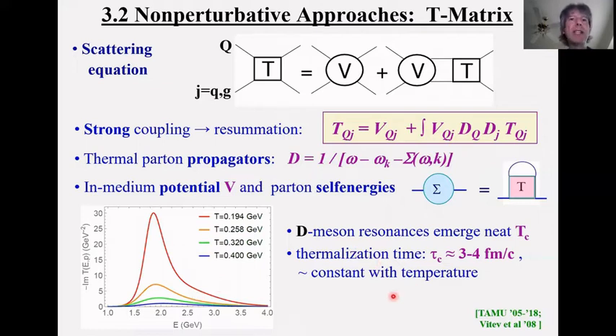That should not be surprising because as you go to lower and lower temperature, the potential should approach that of the vacuum. And if it's a realistic potential, then it should produce the vacuum D-meson mass. And indeed, this peak here is close to that vacuum D-meson mass. Also in this approach, you get rather small thermalization times, down to maybe 3 to 4 fm/c. And you also find that this thermalization time does not really decrease with temperature because you're losing interaction strength. These resonances dissolve, and that is compensated by the increase in the density of the medium, so that at the end of the day, the thermalization time is more or less constant.